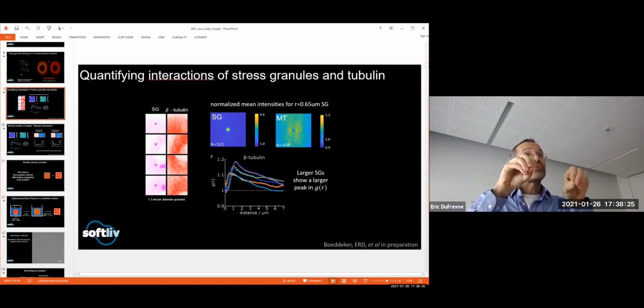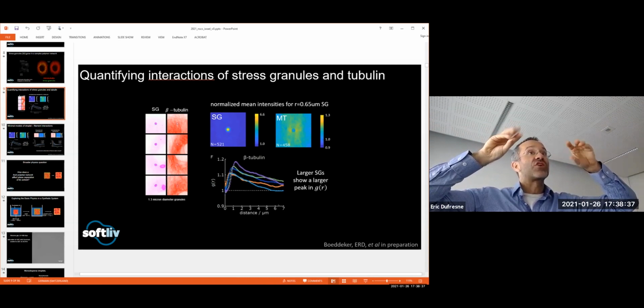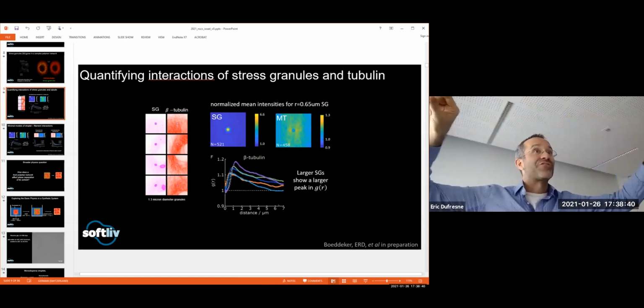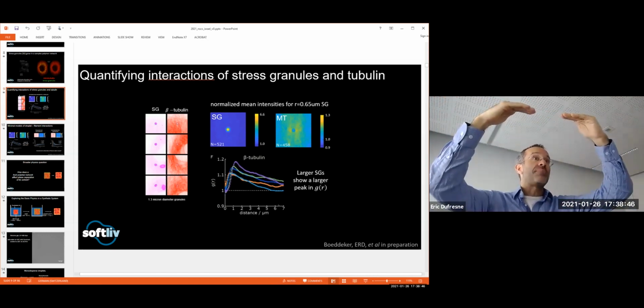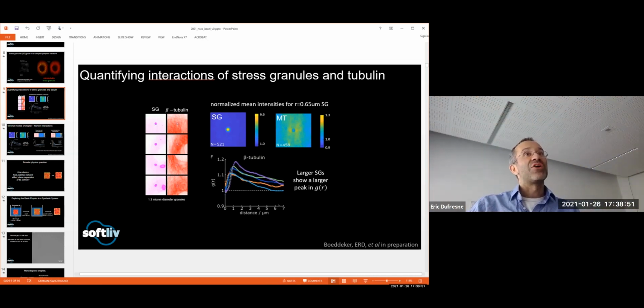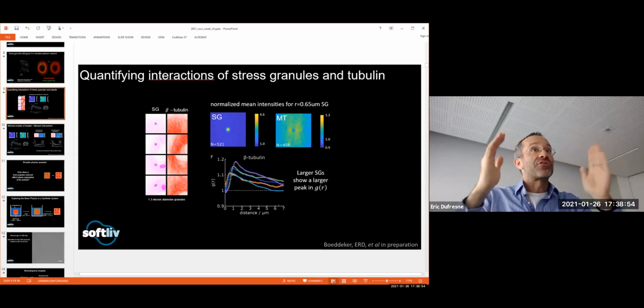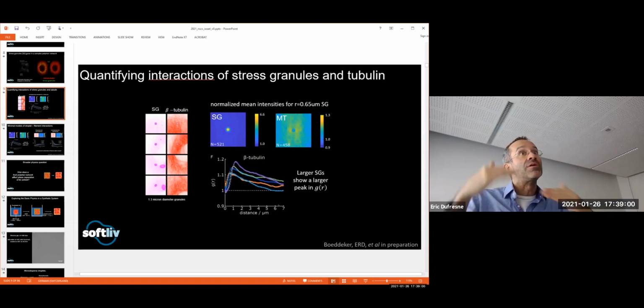If I have droplets in a stiffness gradient next to each other, the material always wants to go to the place where the stiffness is the smallest. So if my material has a free surface, all those droplets near the surface dissolve and we get a puddle on the surface. Over long time scales, eventually all of the droplets will come out and make one big puddle on the surface. If we could think of some way of sealing it off, with really good bonding on all sides, I think these things would be truly stable. But as long as they can escape to the boundaries, they will.